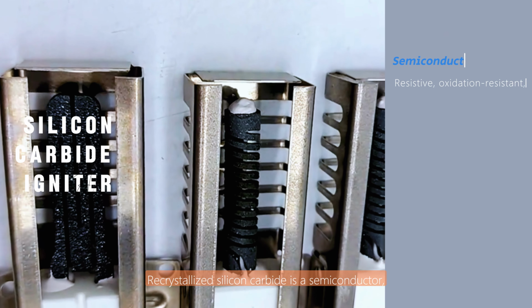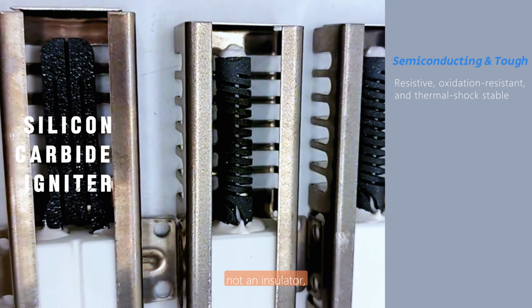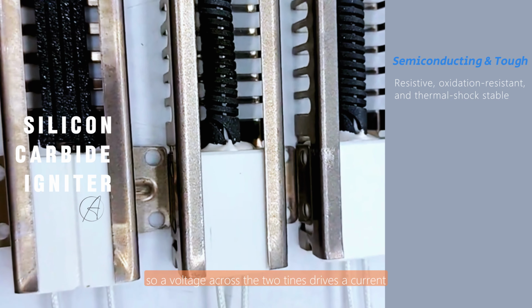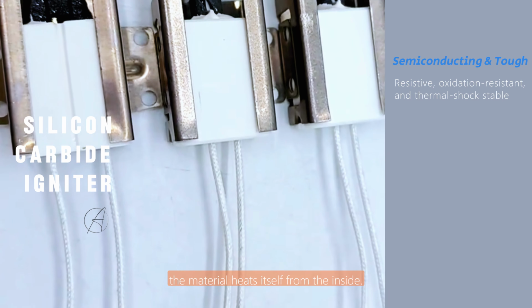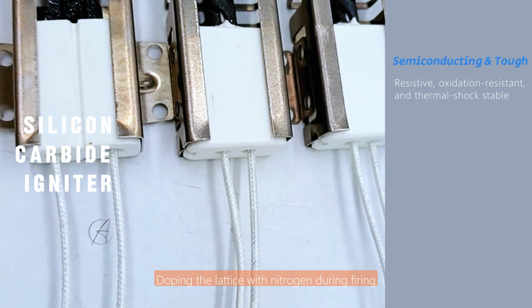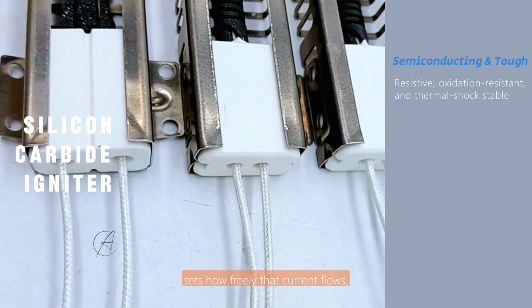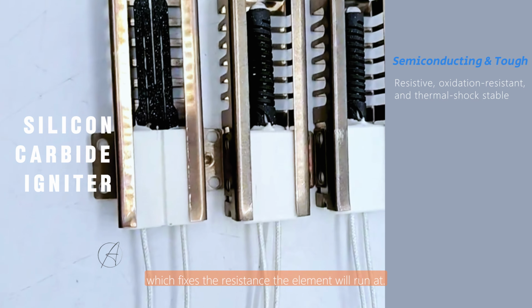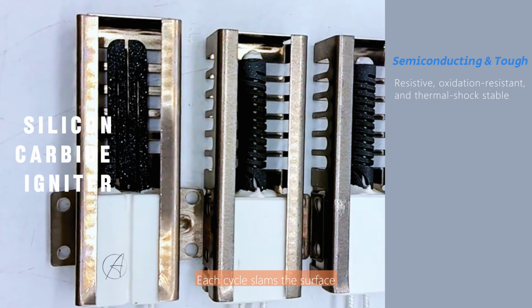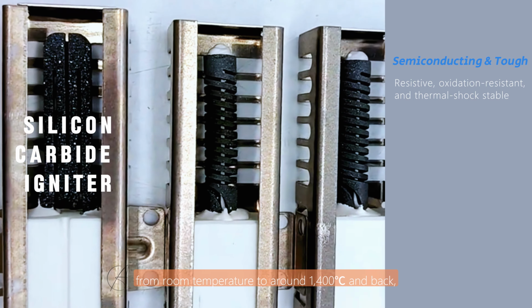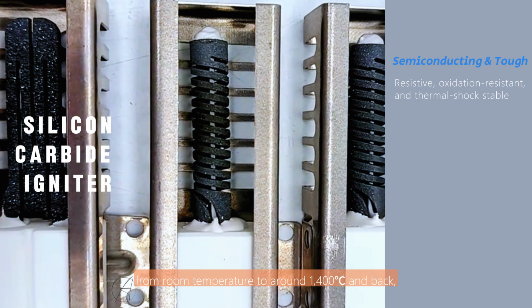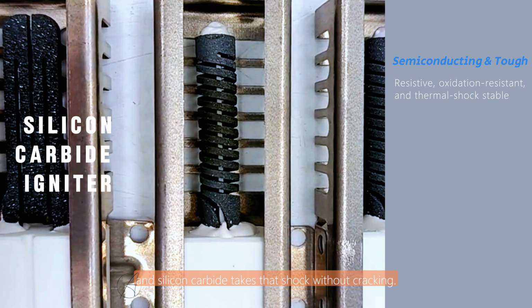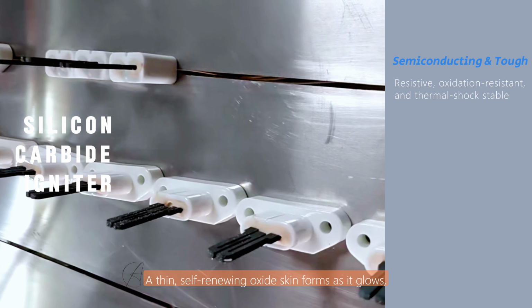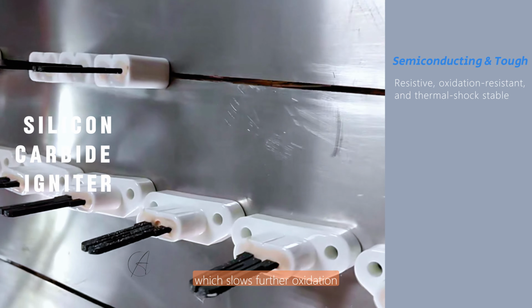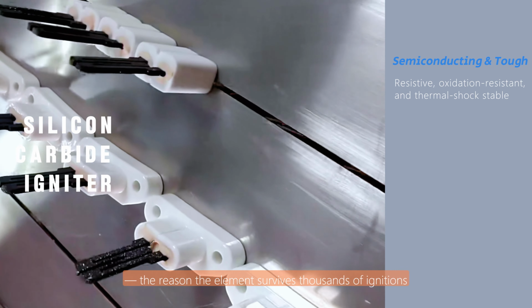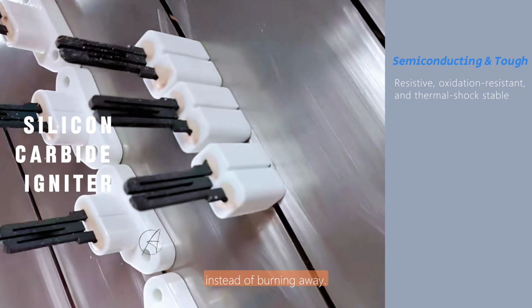Recrystallized silicon carbide is a semiconductor, not an insulator, so a voltage across the two tines drives a current straight through the ceramic and the material heats itself from the inside. Doping the lattice with nitrogen during firing sets how freely that current flows, which fixes the resistance the element will run at. Each cycle slams the surface from room temperature to around 1,400 degrees and back, and silicon carbide takes that shock without cracking. A thin, self-renewing oxide skin forms as it glows, which slows further oxidation, the reason the element survives thousands of ignitions instead of burning away.